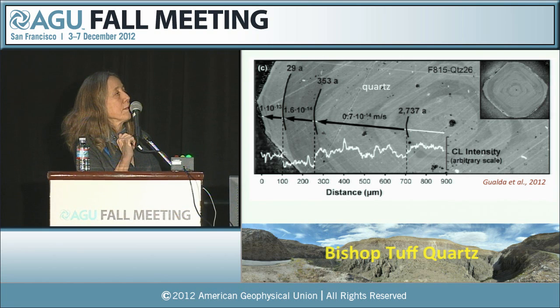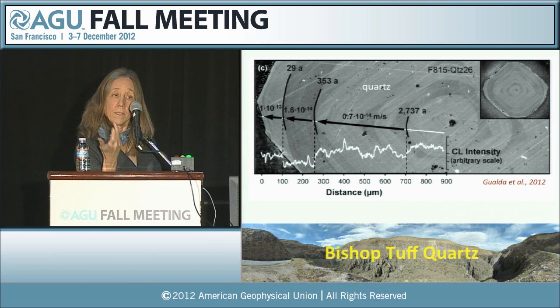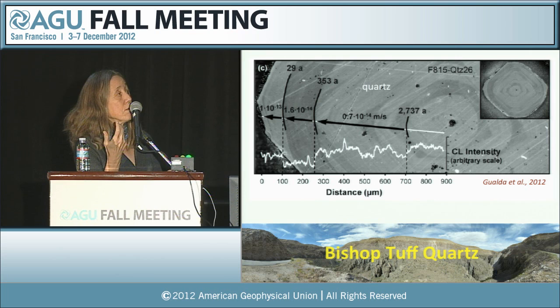And what you can see is timescales here, nearly 3,000 years here, 350 here, 29 here, as you would expect then. This boundary appears to have formed 3,000 years before this boundary here. And from that, then again, you can use the rate of diffusion of titanium in quartz to get at information like, from this we can deduce the rates of quartz crystallization.